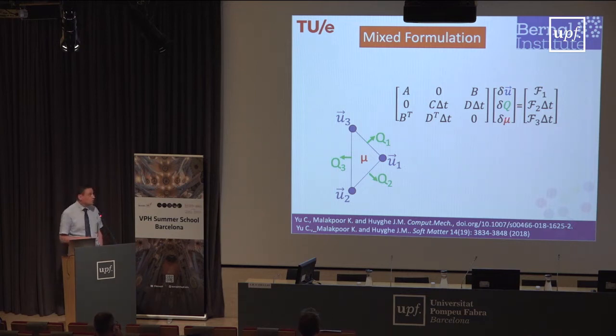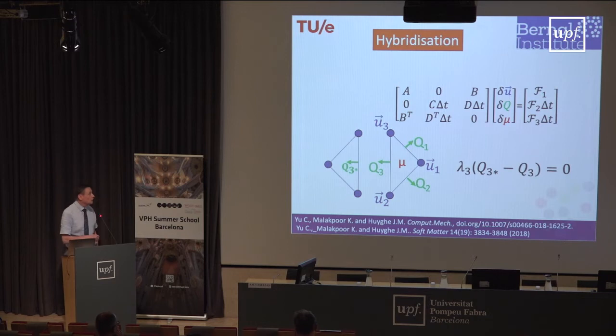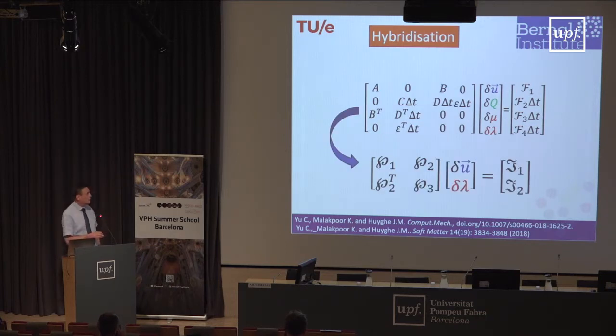And what we do now is enforce these fluxes coming out of one element to be exactly equal to the flux into the other element. So we have two elements next to each other in a big mesh, and so we are forcing this Q3 to be equal to Q3 star by means of a Lagrange multiplier. And what we find is that we can add this condition to our set of equations. And then it becomes a really big equation set with Lagrange multipliers and chemical potential and flux and displacement. And this one will be able to enforce local mass balance.